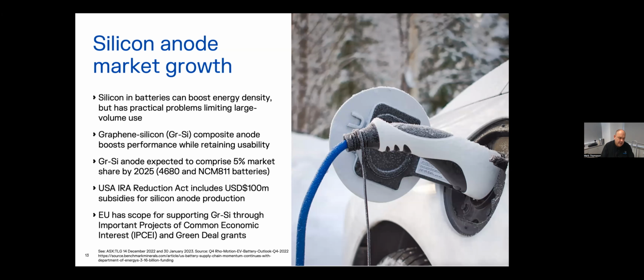What is that demand? Well, we know silicon is like an energy booster. Going back a long time in combustion engines, people would always be trying to put a little pill in the tank to boost things up. In lithium-ion technology, it's silicon. You dope a little bit of silicon into the graphite and you can boost its energy. You get most of the energy boost from small amounts that you put in at the beginning, and after a while that tops out. So we would provide a product that's a 50% silicon containing particle. Our customers would then sprinkle that and mix it into their graphite to dilute it down to the balance and energy density they want.